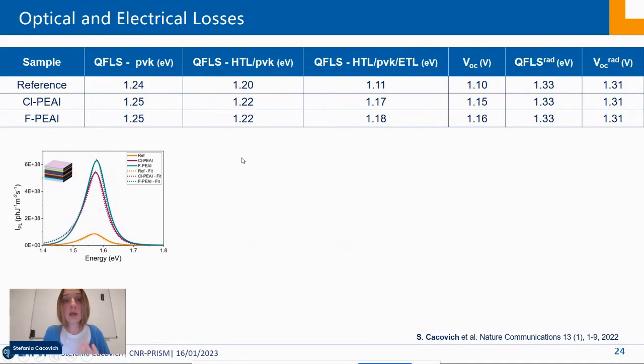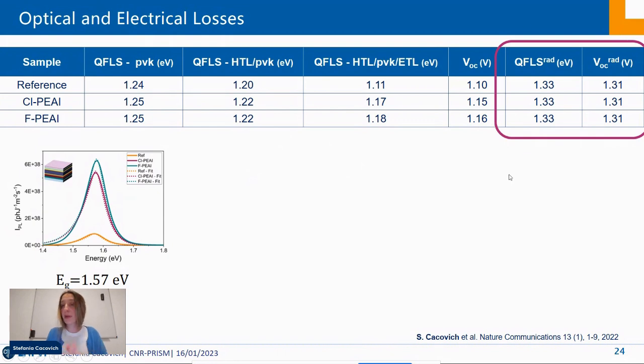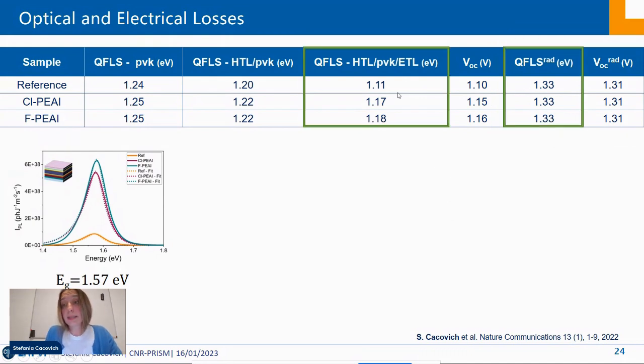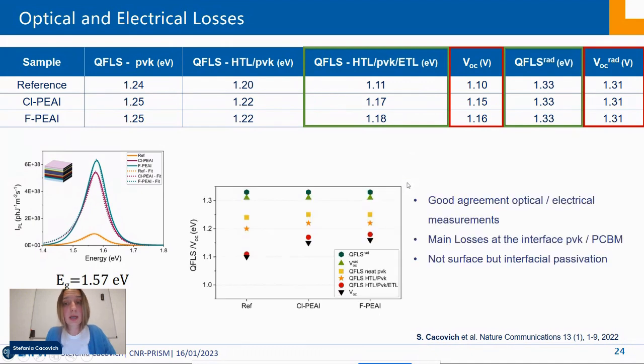So here we have a schematic of all optical and electrical measurements. These are the theoretical radiative limits that we have calculated for the two. You can observe that already just with perovskite on glass, we have a significant reduction in comparison to the radiative limit. And we can see that for the full devices, this is even higher, because when we add an interface, we are also losing energy. And here we have a summary of all the measurements we have done.